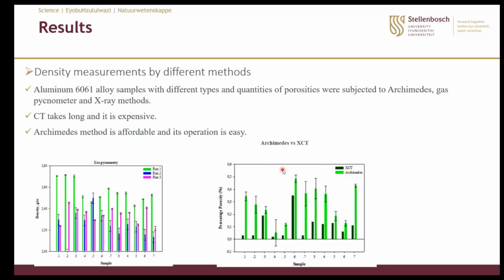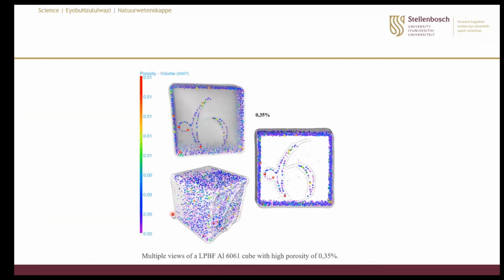With the gas pycnometer, the reason we did not compare it with the other two methods is that it gave us very erroneous values, with porosity greater than 8%. That was the minimum porosity value we got. From these results, we concluded that with X-ray computed tomography, the results are pretty much reliable, and it gives us visual information, for the range of porosity that we had, which is less than 0.5%.